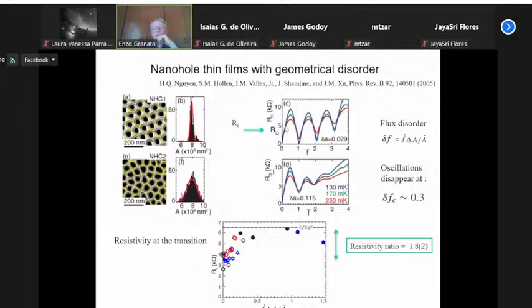This crossing point here is an indicator that there is a superconductor-insulator transition driven by the magnetic field. And so from the crossing point, they can estimate what the resistivity is after the transition. And they find two things.